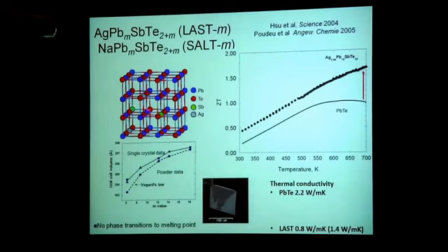So basically you are disordering antimony and silver atoms on the lead sublattice. We thought this would be a good way to lower the thermal conductivity. And then you can do this as a function of M, and you get a smooth variation of the unit cell, which suggests Vegard's law. Vegard's law is used as a diagnostic of having a solid solution, of this thing actually doing what we're supposed to be doing. It's dissolving in there, and the lattice parameters are changing smoothly.